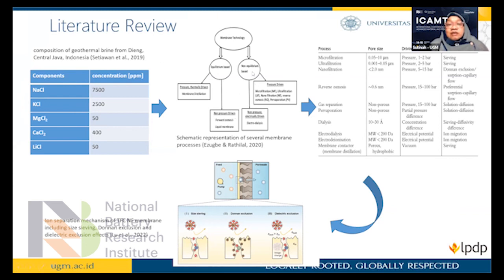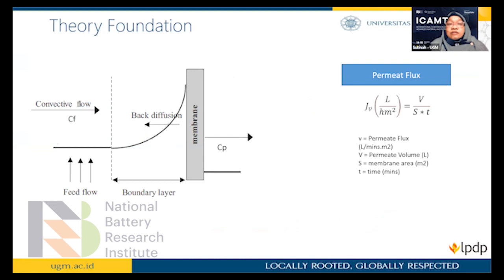Then why do I use nanofiltration? Because nanofiltration is very simple for lithium extraction, and the pore size is under 2.0 nanometers, with a pressure drop of 5 to 15 bars. It has transport mechanisms: the first is size sieving, the second is Donnan exclusion, and the third is dielectric exclusion. And for the foundation of my theory, I searched about the permeate flux. This is the formula of the permeate flux.